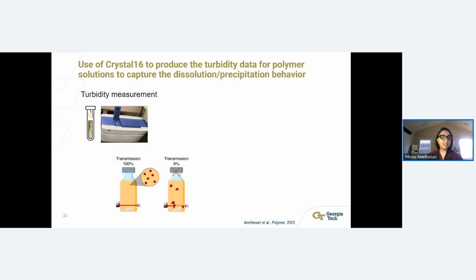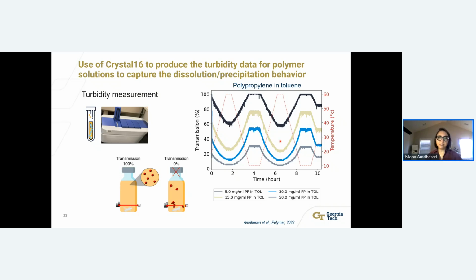For that, we have 1 milliliter of the solvent. When the solution is clear and all the polymer is dissolved in the solvent, you get 100% transmissivity. As the polymer starts precipitating out of the solution or phase separation is happening, the transmissivity drops to a lower value, which is captured by the system. This is a typical result of the Crystal 16 shown here. This experiment has been done in 2 cycles of heating and cooling, shown with the red dashed line, and at 4 different concentrations. The black line shows 5 milligram per milliliter of polypropylene in toluene, and the gray would be 50 milligram per milliliter.